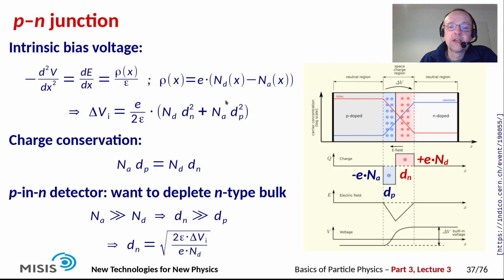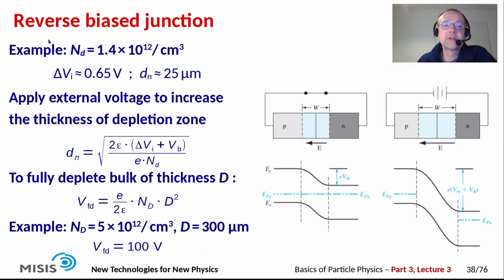And if we do this, because dN is much larger than dP, we can neglect this term in the equation here, and we can calculate the thickness of the depletion zone in the bulk from this simple equation here. Now if we put in a typical value for the doping concentration in the bulk, we can calculate that the intrinsic bias voltage of the junction is 0.65 volt, and the thickness of the depletion zone will be 25 micrometer. Now this is of course much smaller than the thickness of our bulk, which is typically 300 micrometer. But we can increase the thickness of this depletion zone by applying an external voltage here which has the same polarity as the intrinsic bias voltage.